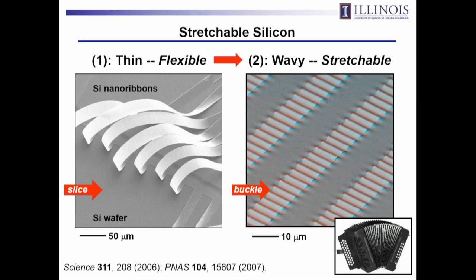But as I mentioned before, flexibility is not good enough for biointegration. It needs to be able to flex and also stretch. And there's no level of thickness that you can take silicon that will render it into a stretchable form. So you need a second idea added on top of that first one in order to create a stretchable form of single crystal device grade silicon. The idea is you take these kinds of materials and you form a composite with a soft elastomer that serves as the substrate. In this case, this is a silicone elastomer substrate,